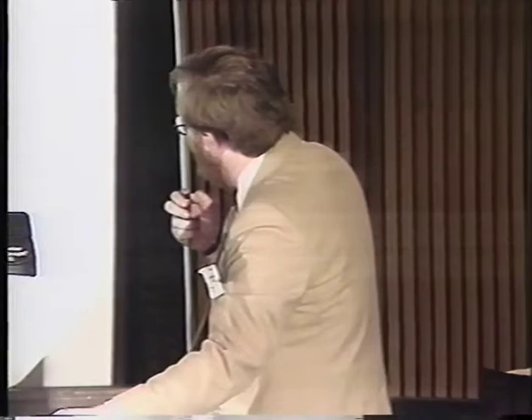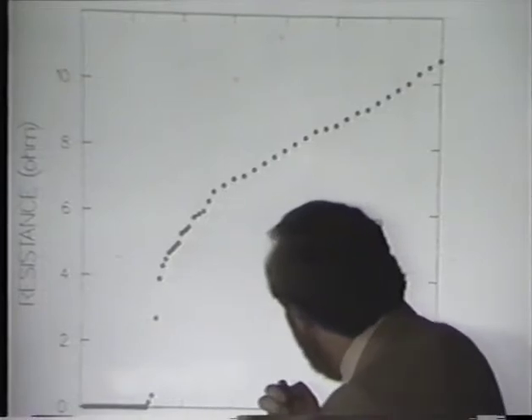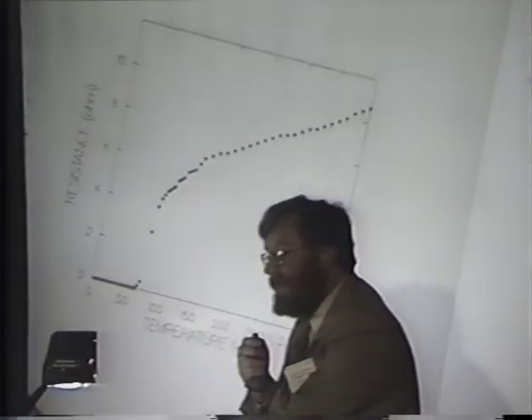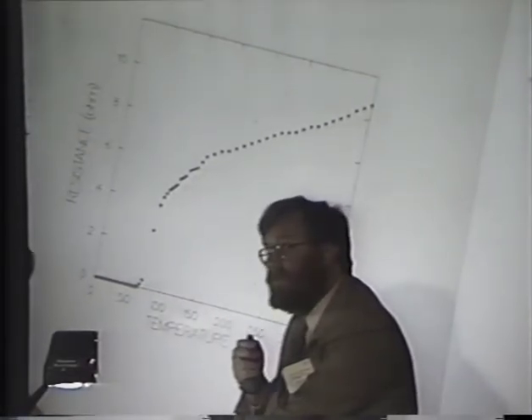The resistance curves are not extremely accurate. Here's the resistance for what it's worth. The midpoint's around 80 here, and there's a resistance here that's a little bumpy, and maybe it turns down at around 100. There's nothing shown in the magnetization, Meissner effect, which reflects this, though.